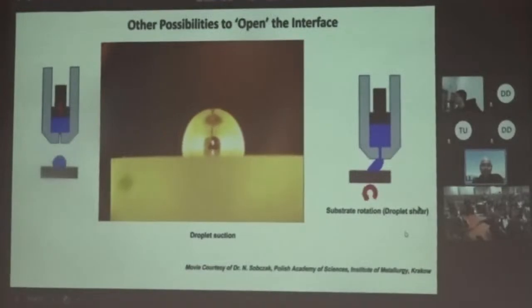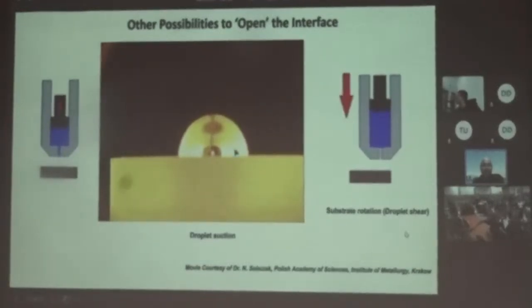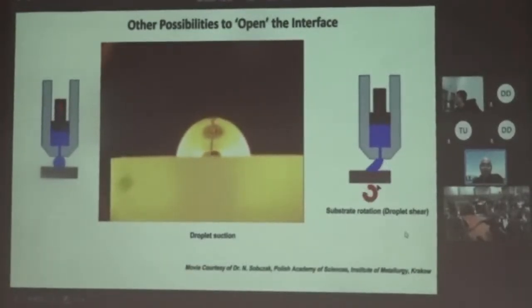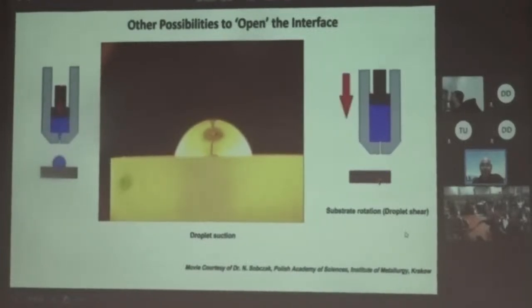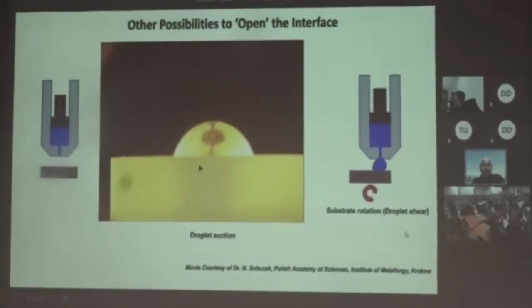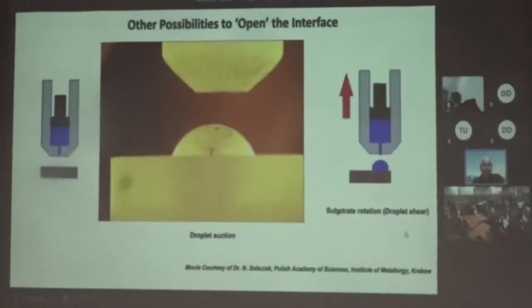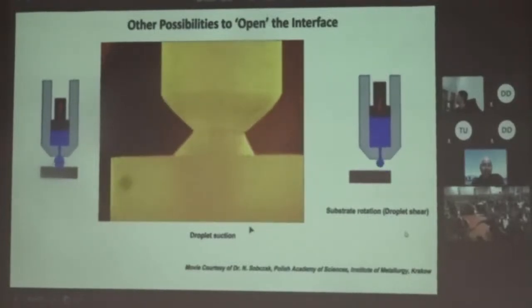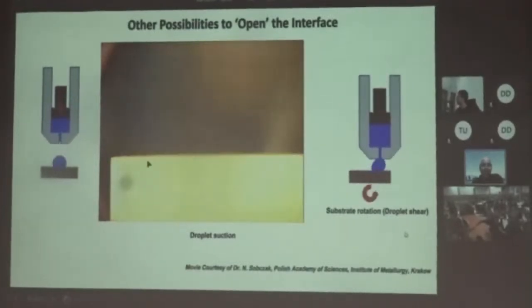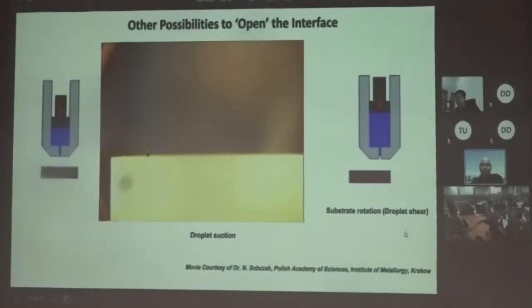The other thing that we have been able to do is to use the drop suction approach, or we can rotate the substrate and see the effect of shearing on interface formation. When we do the suction, after a fixed amount of time, the droplet is pulled out and we are able to open up the surface underneath. This sample can be transferred right from the tester into a vacuum to the X-ray photoelectron spectroscopy system, so it doesn't get exposed to the atmosphere.